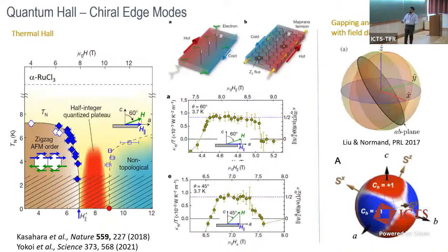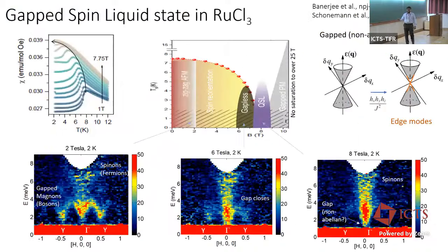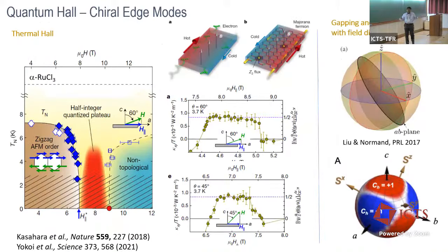And very soon after that, there was this paper by Kasahara and Yuji Matsuda, showing that at 8 Tesla, you see a half-quantized plateau. We know that the results are very debated, but that's what they saw, which seems to be very consistent with the picture that we just saw here. I mean, if we are lucky, that's the picture. What they found is this half-integer quantized plateau right at 8 Tesla, almost up to 5 Kelvin, which is actually a very high temperature.